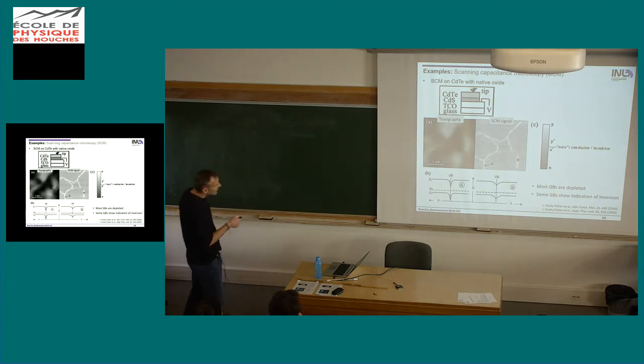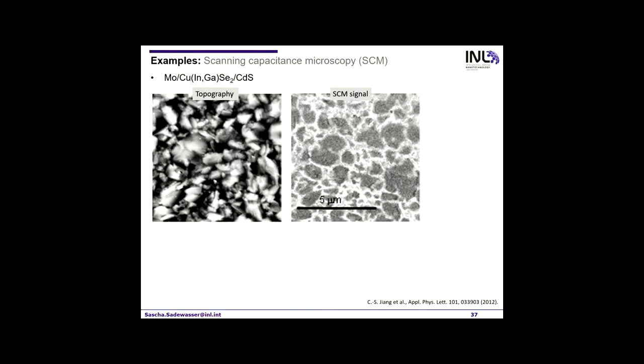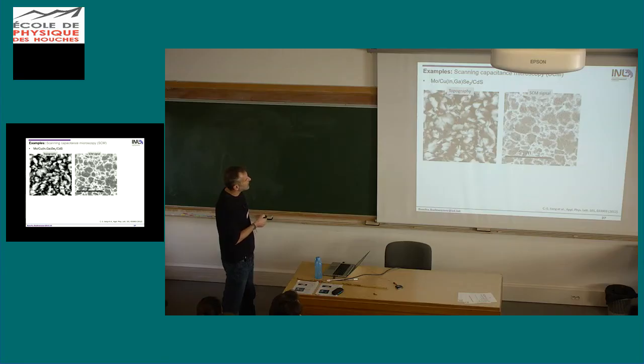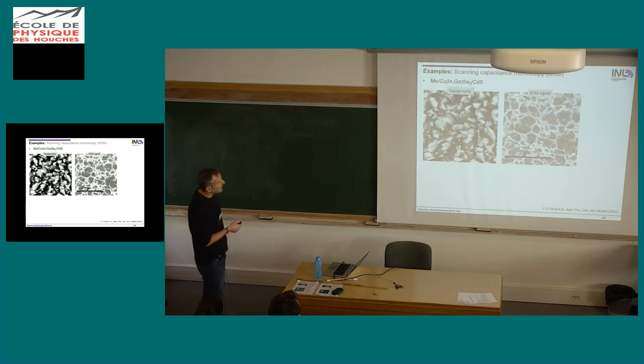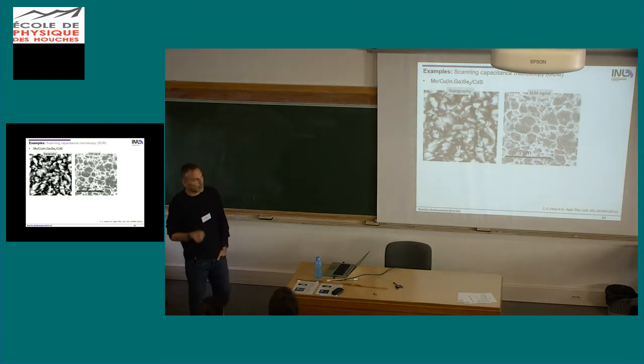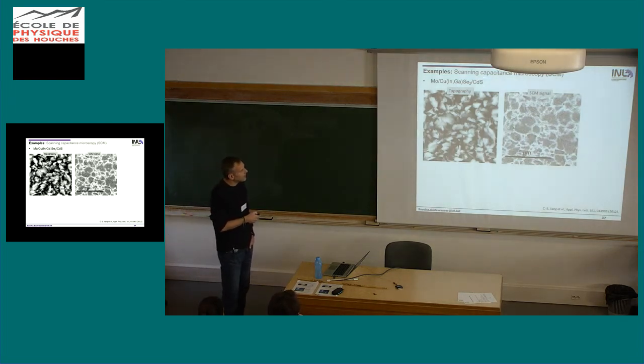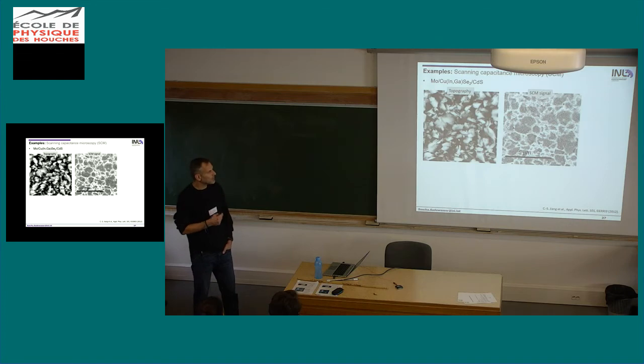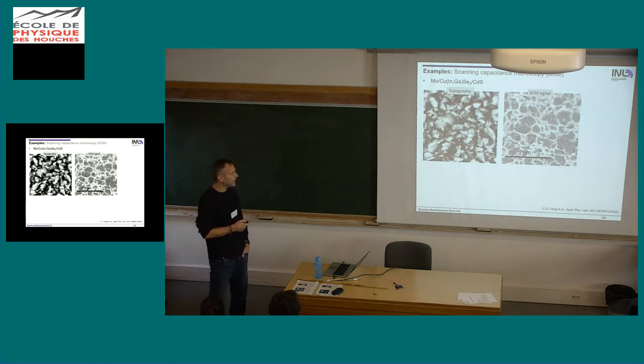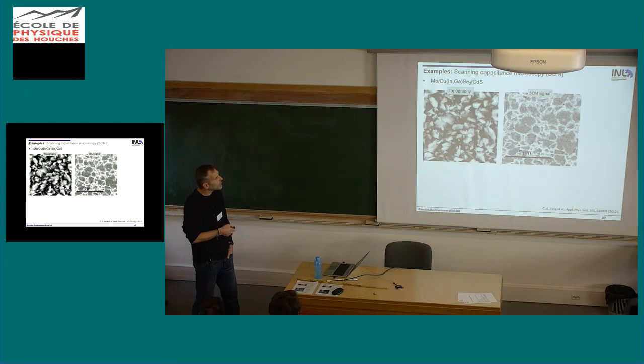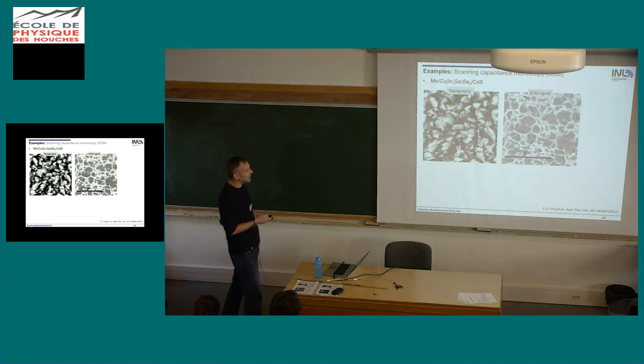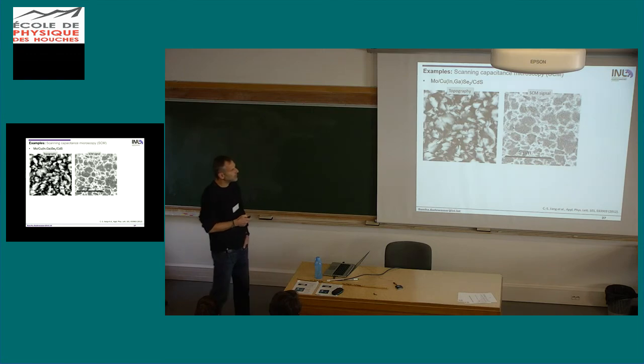So similar things were done also on CIGS. In this case it was molybdenum, CIGS, cadmium sulfide. So here in these experiments apparently the native oxide was not good enough to make a nice capacitor. So the cadmium sulfide was used, and the authors also, so you get a fairly similar result. Also again, lower doping at the grain boundaries. But the authors also said that it was not so easy to really quantify the results because the cadmium sulfide is not really an insulator. It's to some extent semiconducting, and that was complicating the measurements in this study.